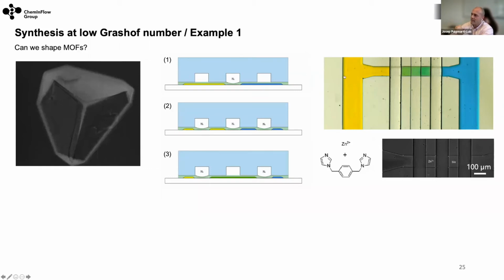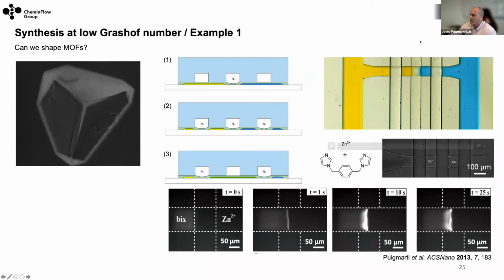But we did this video because, you see, at the end we have at the middle the green color, because yellow and blue generate green, but we could not see what is really happening in the middle. So I didn't believe that we would have this free interface diffusion process, and this is why I decided to work with this coordination polymer. This is an imidazole derivative with zinc. It's known that when these two react, they generate a fluorescent coordination polymer. And look what happens. This is the valve, and here we have the container with the imidazole and the zinc.